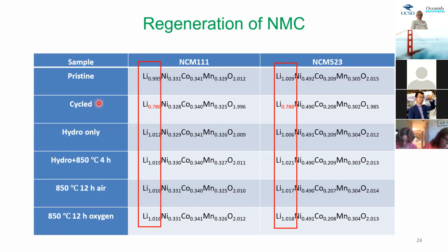After cycling, imagine you have used a cell phone for like a year or a year and a half. So in your cell phone, if you open your battery and you do some testing and you can identify you lose about 23%. Okay, this is basically the reason that is responsible for the cell failure. Okay, so after our process, we try different process, different conditions, you can see, okay, the change of composition back to 1.0, 1.0, 1.0, 1.0, okay. So this basically gives you an idea that how we can basically regenerate the composition back into the desired composition that we have for fresh or for new batteries. Okay, so this is just something I think we can understand more easily.